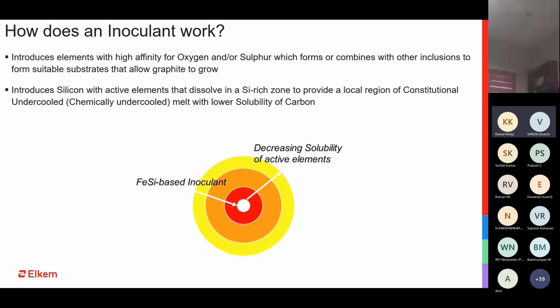And this zone rich in silicon, I mean, I'm talking about very micro level solidification here. So there can be a very small site within your metal, which will be very rich in silicon. And because it is rich in silicon, it gives you the constitutional undercooling. And when it gives you the constitutional undercooling, it allows for the carbon to precipitate out. It reduces the total percent of carbon that can be held by the iron, and thereby makes sure that the total amount of carbon which cannot be held back by the iron comes out or precipitates out as graphite. So basically, this silicon reduces the solubility of carbon in your iron and makes sure that the carbon comes out.